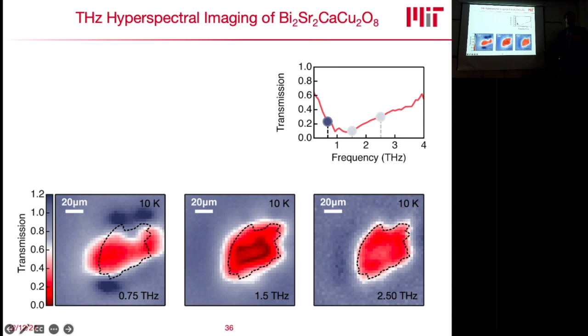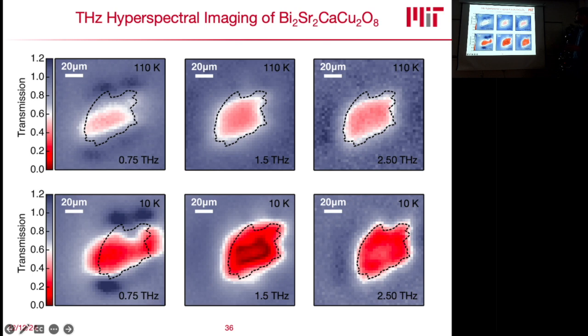So you can see that this confinement changes the frequency-dependent properties of this material dramatically. And we can compare this again to about 110 Kelvin, where you see it dramatically changes. Especially these fine structures that you see inside the sample are completely gone at 110 Kelvin. It's basically a homogeneous excitation.